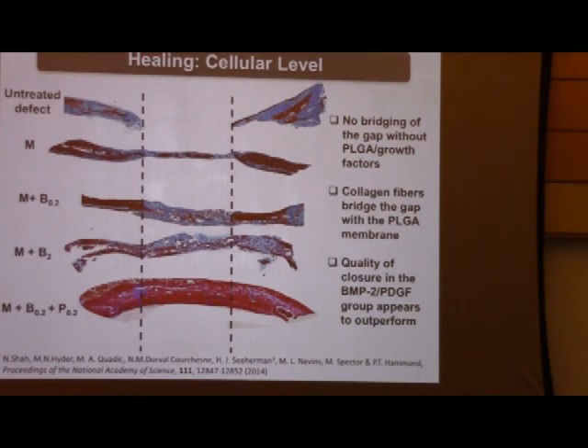We can actually take sections of that bone and look at them after staining for blood vessels and bone in the microscope. And what we can see is that the untreated defect, of course, has this big gap in it. So these are the edges of the skull, and this is where bone does not exist. If we just put a membrane of PLGA with nothing on top, you don't get bone, but you get this kind of bridge of collagenous tissue. It's kind of like a scab. Fibroblasts will crawl across the membrane, deposit collagen, but it's a very weak kind of matrix that it forms. So it's not any kind of load-bearing tissue.